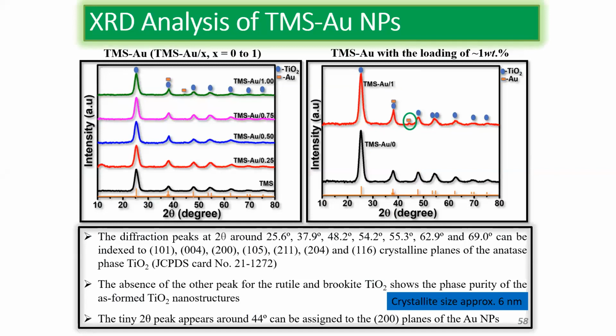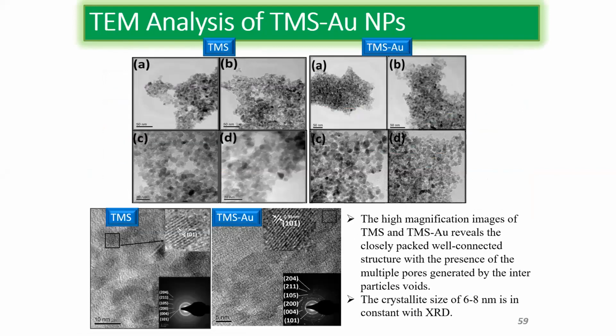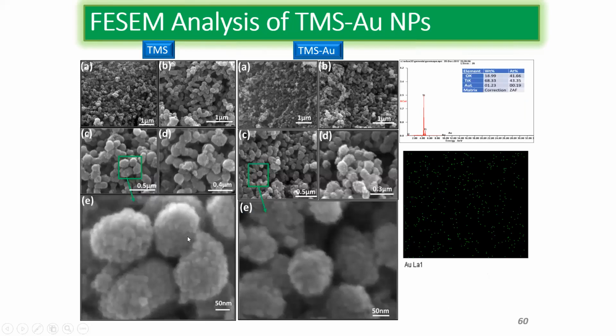So some XRD of those particular materials, and this is the TEM. The TEM image shows the crystallite size is somewhere around 5 to 10 nanometers, which is really very small. The particle size that I am showing here is quite big, somewhere around 200 nanometers, but the small crystallites are only 5 nanometers. I found this material very suitable for DSSC applications, because small crystallites give better electron transport and a bigger particle size gives better light scattering. The light will scatter more, as we know from the Rayleigh scattering phenomenon.